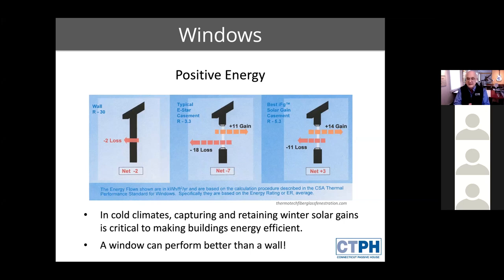Now, everything upends. It's almost counterintuitive. By the improvement in the window, including the films and the orientation, we've boosted the gain from plus 11 to plus 14 and dropped the loss from minus 18 to 11. And we end up actually gaining energy in the building. In fact, it means the window is better than a wall without a window in the big picture. The window can perform better than the wall.